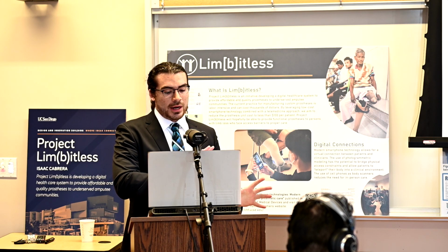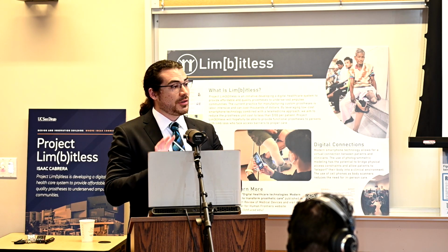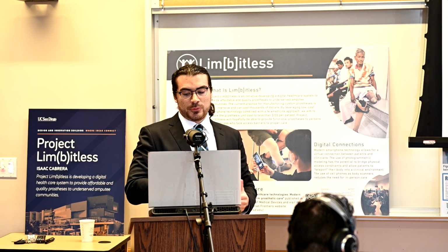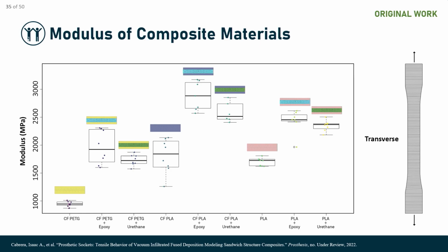However, there's a totally different story when we look at the transverse properties. When you're 3D printing these materials, they're very anisotropic, meaning they're stronger in one direction than the other. The transverse direction is by far and away the weaker direction, and that also applies to properties such as stiffness. And you can see here quite clearly that infiltrating with either the urethane or epoxy really increased the stiffness of our transverse direction.